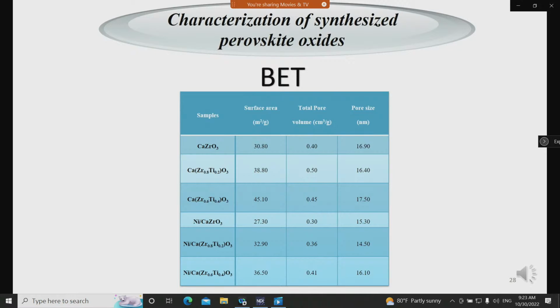Overall, the pore size of the perovskite is around 16 to 17 nanometers, and this pore size is larger than that of alumina and zeolite. For gamma alumina, the pore size is around 6 nanometers. So this large pore size allows more effective distribution of the active metal and better dispersion. In fact, the pores act as channels for accessing the inner parts of the catalyst. The ease of accessibility of gas molecules as the feed to the catalyst active sites ultimately causes increased conversion as well as hydrogen production.